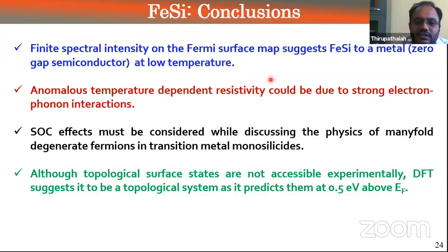So with this, I come to a conclusion that finite spectral intensity on the Fermi surface map actually suggests that FeSi is not an insulator or semiconductor, but at low temperature it acts as a metal. And anomalous temperature resistivity could be due to strong electron-phonon interactions. Of course, also one should think about spin fluctuations as well. And importantly, one must consider this spin-orbit coupling effect while talking about the physics of multifold fermions in these transition metal monosilicides.